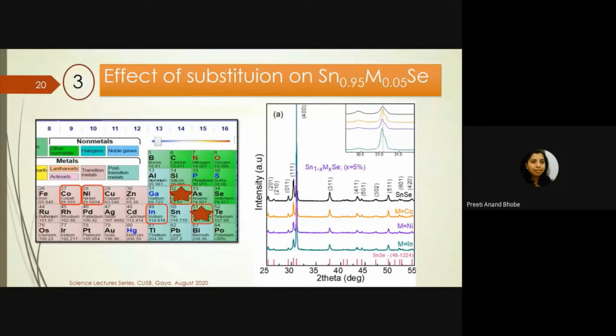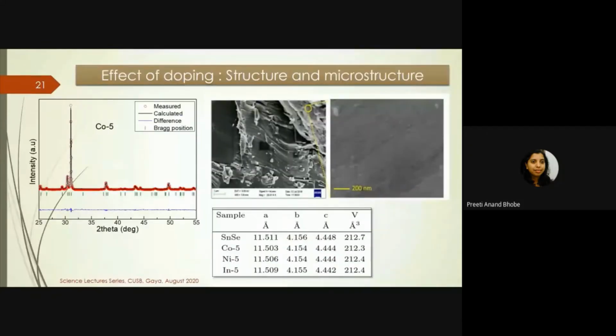The XRD tells us that a very phase pure material is formed. And if one looks at the microstructure, because that was the interest, since the microstructure had changed drastically when we put in copper, what happens to the microstructure when we dope with cobalt, nickel or indium? To our surprise, unlike the case of copper, we do not find any microstructure change in these dopants, in cobalt, nickel or indium doping. There is no microstructure change. The layered structure of the material is maintained. The microstructure is the same in all the materials.